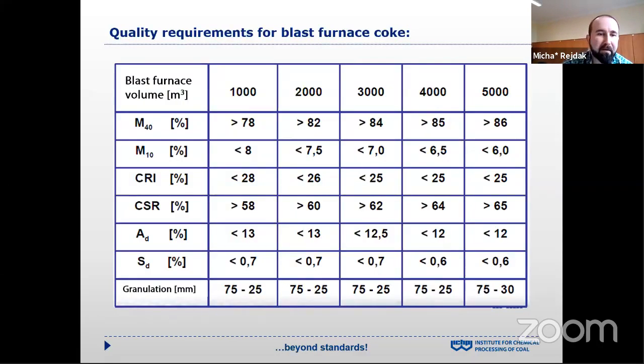So coke is to be stronger. It should be with higher mechanical strength to ensure the proper permeability of the feed. And of course, it shouldn't be degraded. When we have a higher reactivity and lower coke strength after reaction, the coke is diminished too fast, and of course the operation effectivity of the blast furnace is decreased.